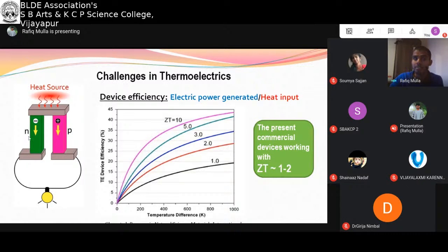If thermoelectric materials have ZT equal to 1, we have this kind of efficiency. If we use ZT equal to 2, this is the efficiency of the device. For 3, this is the efficiency. For 5, this is the efficiency. So presently we have roughly 1 to 2, and by applying 200 degrees of temperature difference across the device, we can see we produce about 10 to 12% efficiency. Of course, at high temperature it is more, but typically we can produce from different sources up to 200 degrees Celsius temperature difference. So the efficiency of these devices is very small, which makes them non-popular for different reasons.